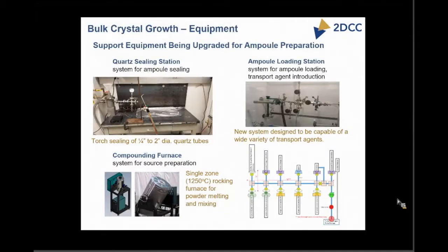In support of all this, we're putting together some support capabilities, namely 3 things. The quartz sealing station is going to be upgraded, turbo pumped for high vacuum capability, rapid pumping of up to 2-inch diameter quartz ampules for sealing for growth or annealing. There's also going to be an ampule loading station, part of the 2DCC, that would allow for incorporation of various transport agents during this loading process, and then a compounding furnace so that materials could be synthesized outside of the Bridgman system and compounded there and then go into the Bridgman process for growth.